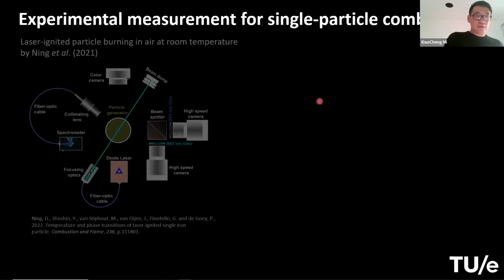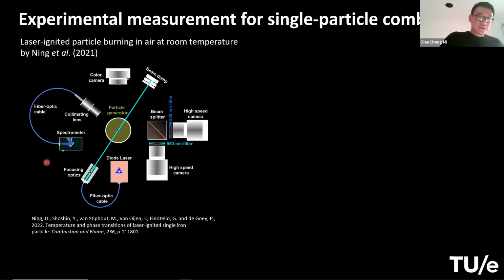We need to compare the results with some experimental measurements. One experimental measurement was done by our former PhD student Daoguan Ning, using laser-ignited particle burning in air at room temperature. This is the top view of the setup. The particle is injected in the center of this setup, ignited by laser, and the temperature is monitored by this two-color pyrometry.